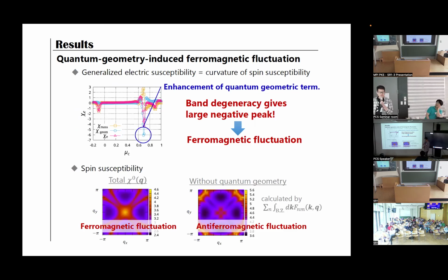Okay. So now we have ferromagnetic fluctuations. Here I am showing the chemical potential dependence of the curvature of the spin susceptibilities, and it shows large negative peaks around the Dirac point. So this means that the band degeneracy gives the ferromagnetic spin fluctuations. Consistent with this fact, we obtained the momentum dependence of the magnetic susceptibility like this, and it actually shows a big peak here.